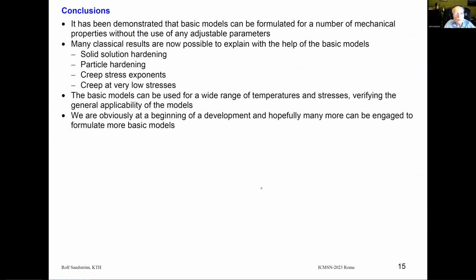I come to my conclusions. It's been demonstrated that basic models can be formulated for a number of mechanical properties without the use of any adjustable parameters. Many classical results are now possible to explain with the help of the basic models: solid solution hardening, particle hardening, creep stress exponents, creep at very low stresses. The basic models can be used for a wide range of temperatures and stresses, verifying the general applicability of the models. We are obviously at the beginning of a development, and hopefully many more can be engaged to formulate more basic models.